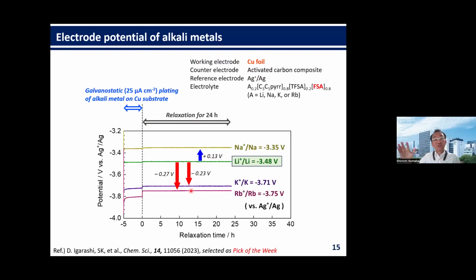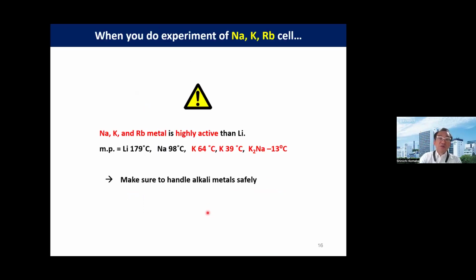So we note that the potential window is wider for potassium and rubidium if we reasonably assume that the anodic limit is the same. I mean, the anodic limit is determined by the solvent species. When we use metallic sodium, potassium, and rubidium as the electrode, we should make sure to handle these metals safely, because they are of course more reactive than lithium, and also the melting point is lower than lithium. This means after a heat-generating reaction, potassium, sodium, and rubidium are very, very dangerous.